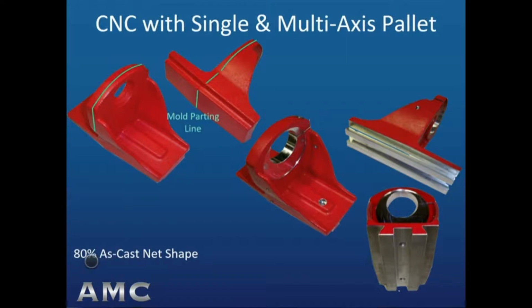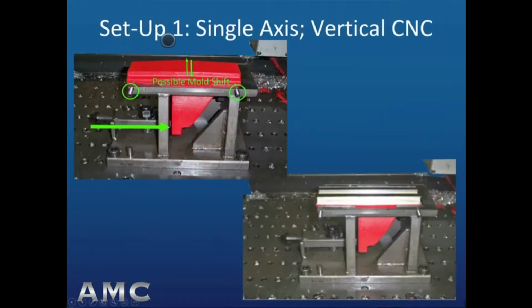The casting is very simple. It is an air-set aluminum casting formed vertically in the mold with no cores. The as-cast geometry at the upper left shows how the mold is parted with the gusset features formed in the lower half, or the drag half of the mold. The casting is gated and risered at the parting line of the mold, on what becomes the dovetail machined feature. The first setup is a single axis vertical milling of the dovetails on the bottom of the casting.